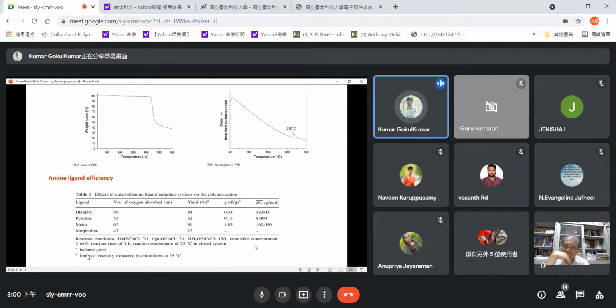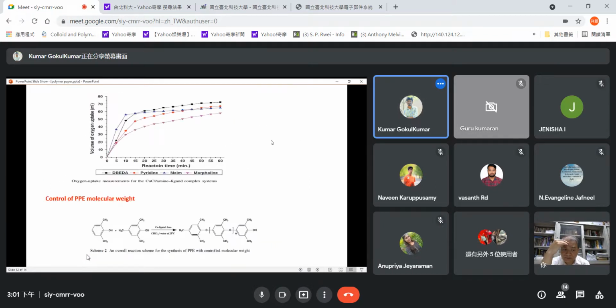This figure shows the TGA and DSC thermograms. The thermal decomposition temperature from TGA is 438 degrees Celsius, and the glass transition temperature is 219 degrees Celsius. Next is the amine ligand efficiency. This figure shows the efficiency of the copper(I) amine complex catalyst system with various amine ligands such as DBEDA, pyridine, melamine, and morpholine.